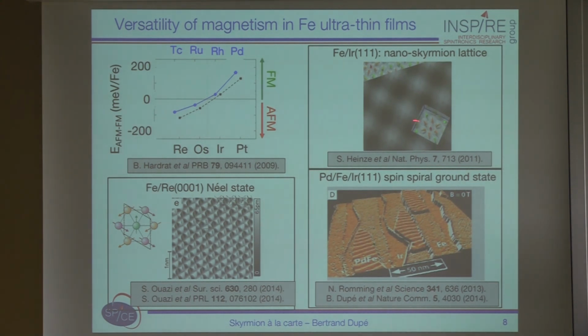And you see that instead of having this ground state, which is a very fast rotating spin texture, now you have a spin spiral. This is a spin polarized STM measurement done in the group of Wiesendanger in Hamburg, where you see a succession of black and white stripes, which corresponds to the magnetization being up or down, depending on the direction of the tip.